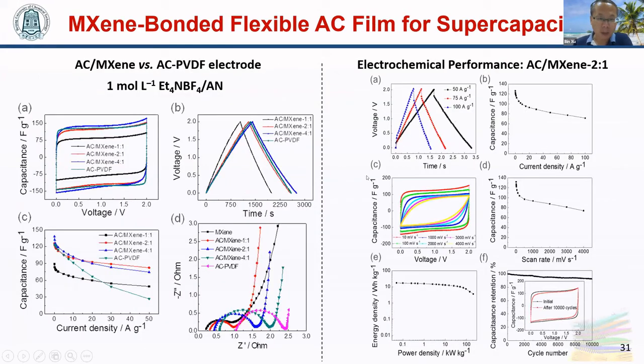We measured the electrochemical performance of this film in a symmetrical two-electrode system with organic electrolyte. You can see, compared with the PVDF bonded electrode, the MXene bonded electrode shows higher capacitance, better rate performance, and much lower resistance. This is because of the metallic conductivity of MXenes. The electrode also shows a very good rate performance. It can endure a very large scan rate of 4 volts per second. This is a very large scan rate.